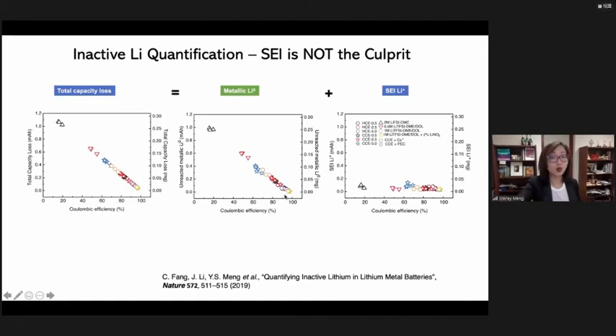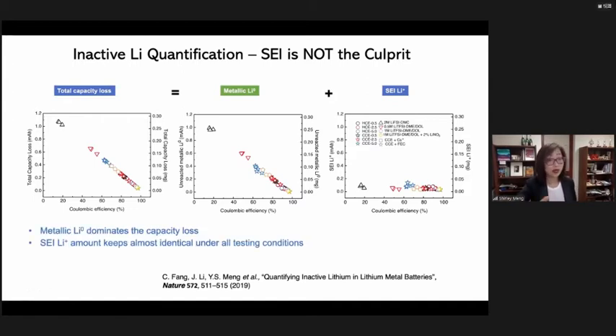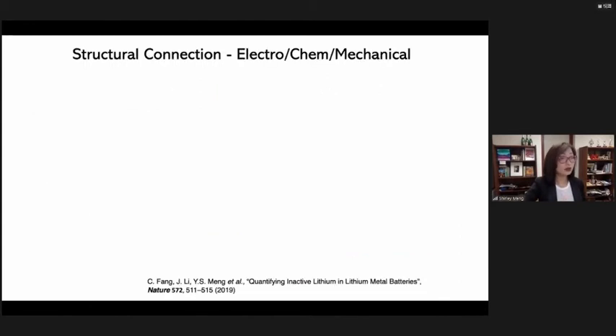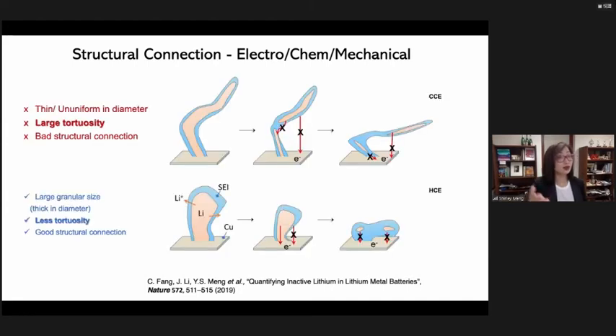So when people are now working on high efficiency electrolytes, I want to emphasize the SEI is still very important, right? This work is already 2 years ago, to showcase that first we need to understand and control the microstructure of the lithium metal, and the SEI is not the main reason for the low Coulombic efficiency of lithium metal batteries. Because of this discovery, we can now think about other effective strategies to ensure 100% reversibility of this lithium metal deposition and stripping.